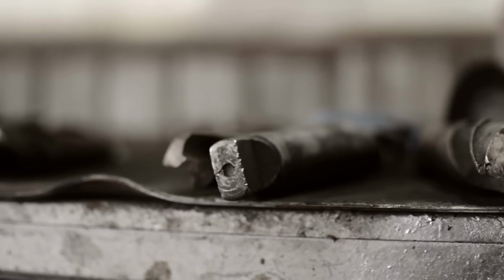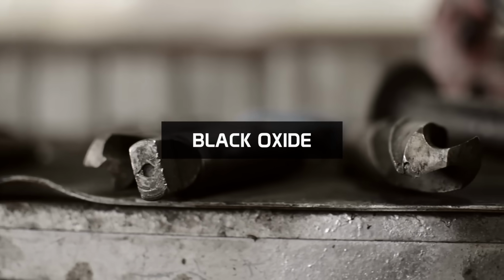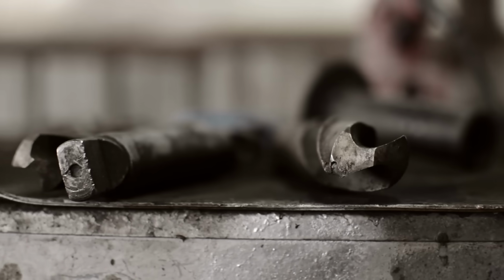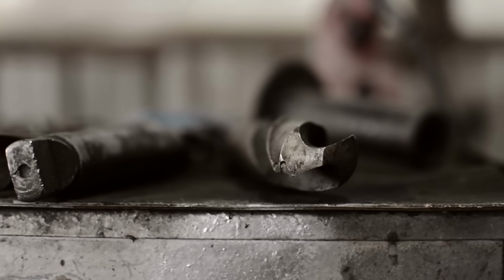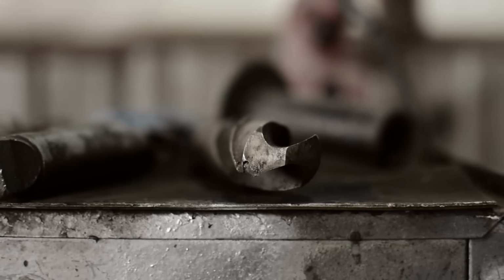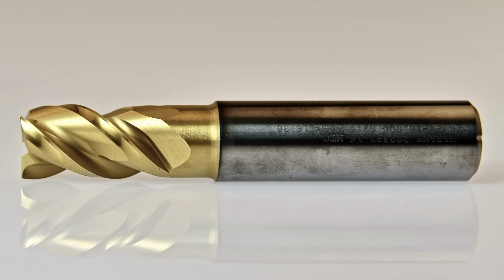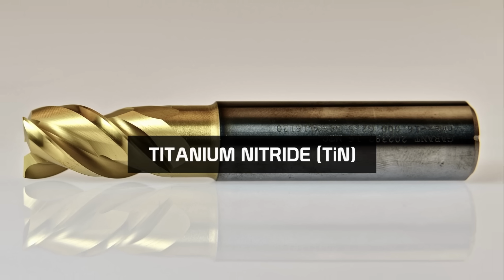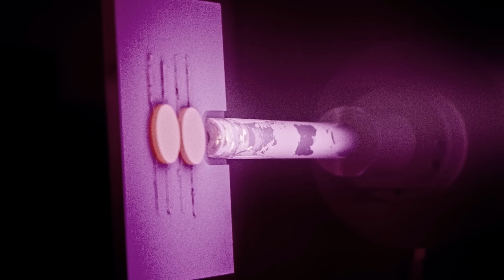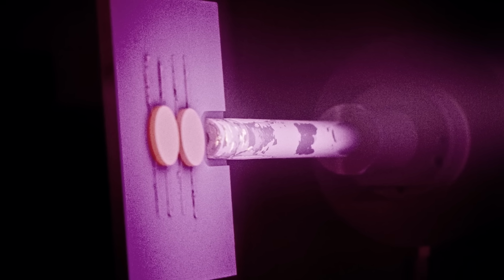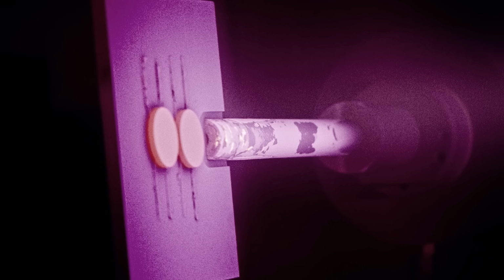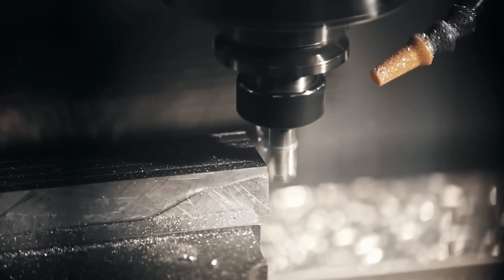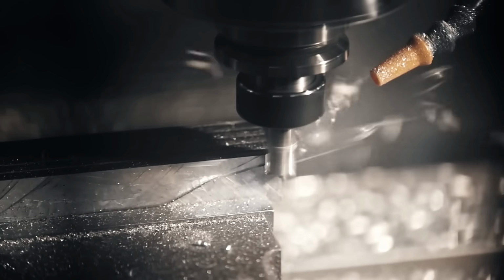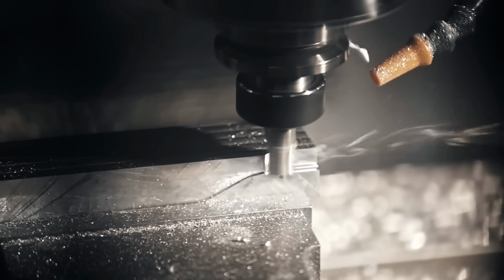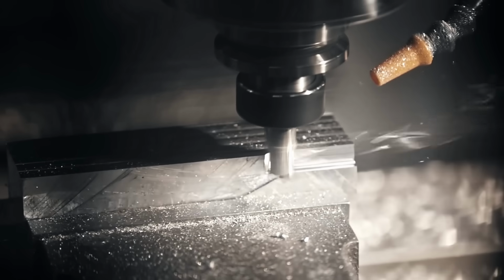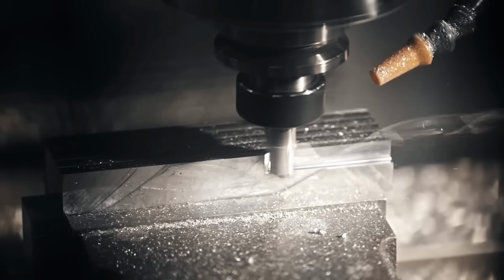One of the oldest and most common coatings is black oxide. Commonly appearing on drills and taps, a black oxide surface treatment is done to deter the buildup of work material on the tool. One of the more contemporary coatings used on high-speed steel is titanium nitride. This coating is applied by the process of physical vapor deposition at a temperature low enough to prevent significant changes to the tool's heat treatment. Titanium nitride can extend the cutting life of a cutting tool significantly, by as much as 3 times, and permit operating speeds to be increased by up to 50% when compared to raw tooling.